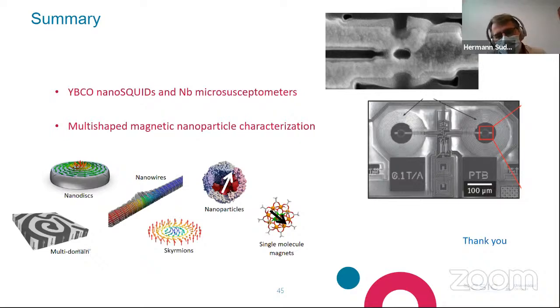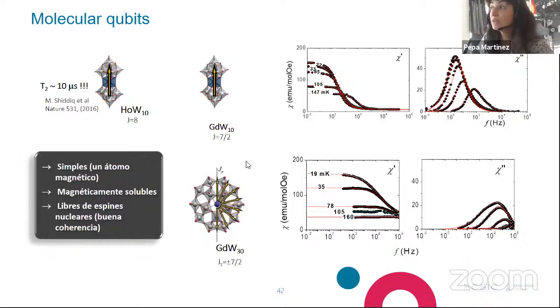Yeah, indeed. For instance, in these measurements here, what these peaks tell us is that the paramagnetic moment is being blocked. But at lower frequencies we also demonstrated that this process of thermalization of the spin with the thermal bath, which is why the spin follows the magnetic field according to the Curie law, is taking place through a quantum process. We could demonstrate that by comparing the expected relaxation times from a quantum process with classical relaxation mechanisms like Orbach processes or the direct process.